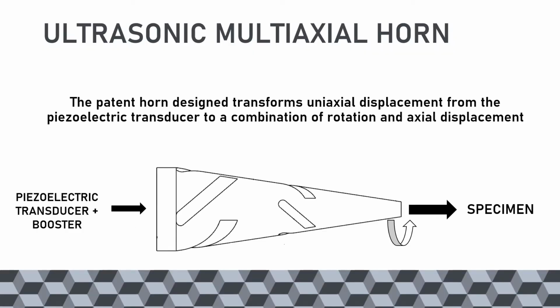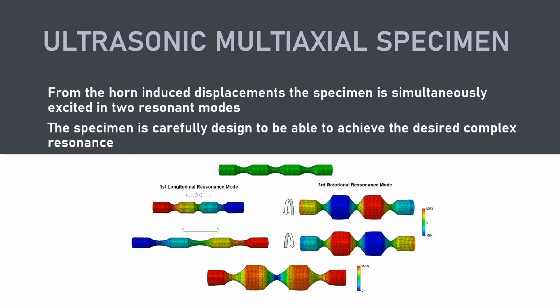The patent horn is the essential component that gives the ability to induce tension and torsion simultaneously. It transforms partially the actual displacement that comes from the piezoelectric transducer and the booster to a combination of rotation and actual displacements that are induced to the specimen. Now, from the horn-induced displacement combination, the actual and the rotational displacement, the specimen is simultaneously excited in two resonant modes. To have a rotational resonant mode and a longitudinal resonant mode at the working frequency, the specimen was specially designed with three throats, two secondary throats at the edges and one main throat at the center.